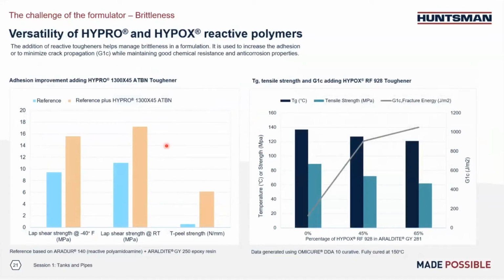So now let's look at some data. By adding toughener, we can see the performance improvement. On the left side, we're adding HYPRO 1300X45 ATBN into the amine side. The reference we use is based on GY250 and Ancamine 140. By adding the toughener, we can improve the overall system adhesion. In this test, you can see lap shear strength at room temperature, and by using toughener, we can improve performance almost 50% compared to the reference control. At a lower temperature, such as -40 F, which is also -40 degrees C, you can see the improvement is almost doubled. We also noticed very good improvement in terms of T-peel strength.